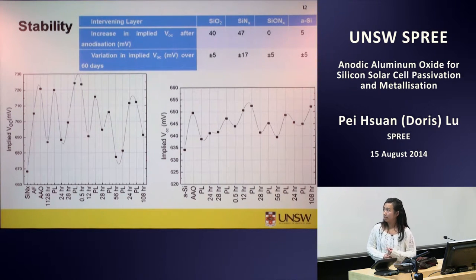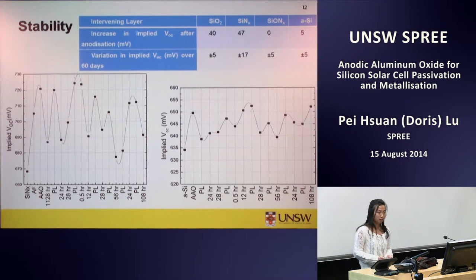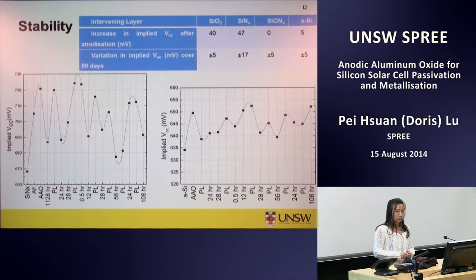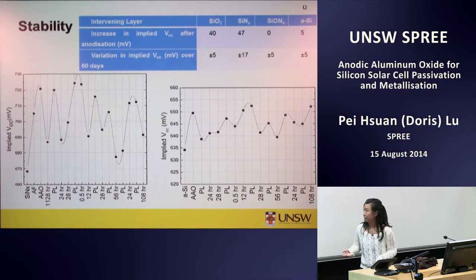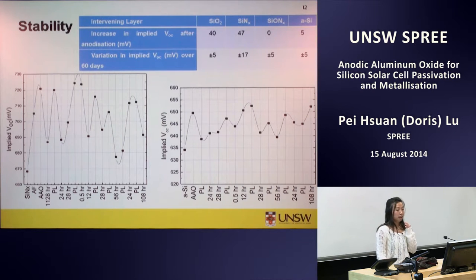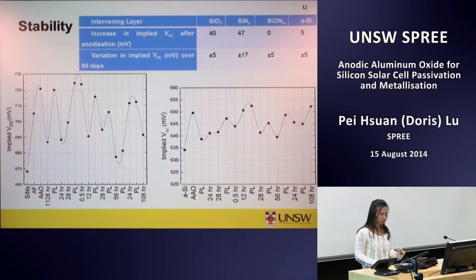Compared to amorphous silicon, the variation is relatively small, within 5 millivolt, except the first PL image makes the lifetime degrade, which suggests the amorphous silicon degradation is induced by light at the first PL. And for the rest of the PL images, it doesn't give a very conclusive result whether it's a variation or just measurement error.